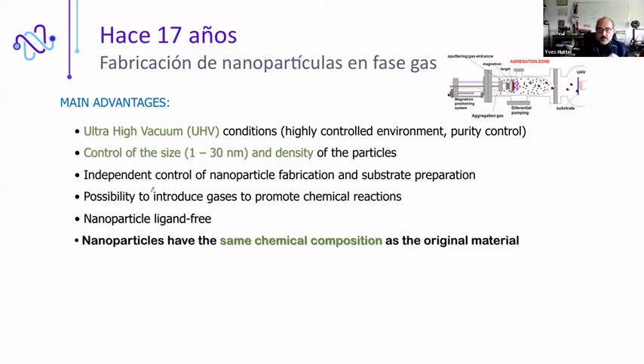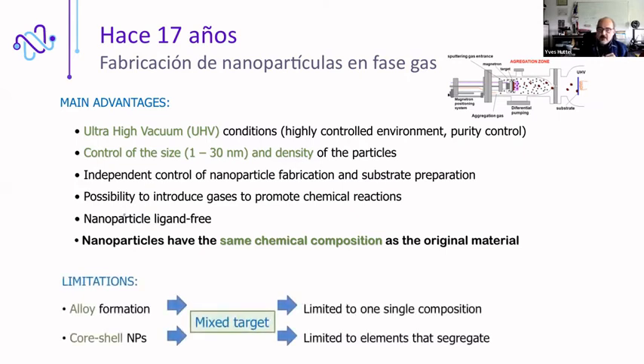This last point can be an advantage, but also a limitation, because when you want to form alloys or core-shell nanoparticles, you have to use a mixed target. And for the formation of the alloy, you should be sure that the elements of the nanoparticles will not diffuse inside the nanoparticle. And then when you want to make core-shell nanoparticles, you have to choose a combination of elements in such a way that one element will migrate to the surface, for example, in order to form the shell. So this is limiting.